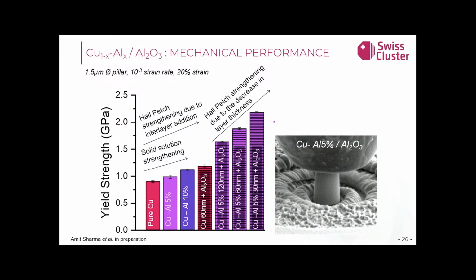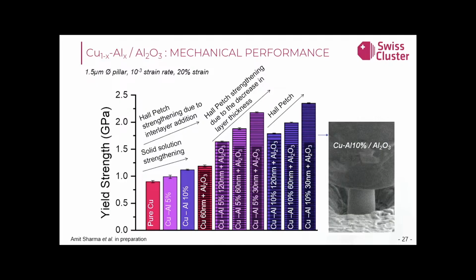So this is a scaling effect due to the grain size refinement of the copper aluminum 5%, but there's a significant increase because of adding aluminum oxide. So this really shows that what is responsible for this high increase in the mechanical behavior is the addition of the ALD films. And we see this scaling effect also with the copper aluminum 10%. So this becomes a good strategy not only to increase the mechanical behavior, the yield strength of the material, but also we can increase the ductility of this type of material. And I will show another last example.